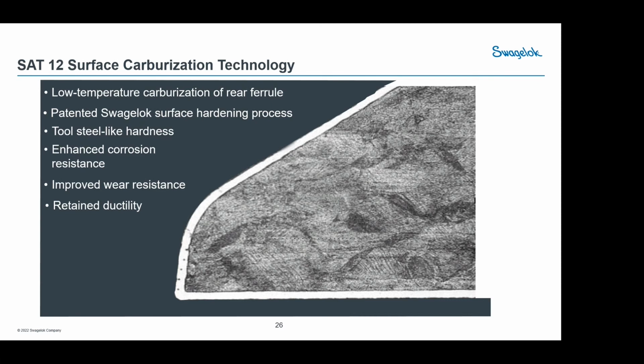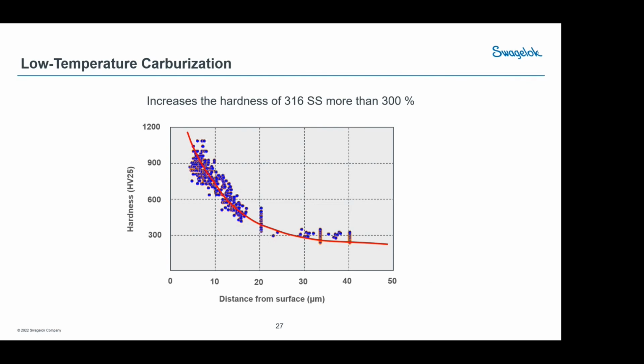Most importantly, though, as this moves through plastic deformation, it does not crack. So remember, cracks cause hydrogen to be able to enter into the products and cause issues. There are other ways to harden stainless that are chemical, but they crack as soon as they start to move. So that's not a great way to make that work. So it really adds to wear resistance and gives us a very hard surface. Up near the surface, where we've added all the carbon, we're up into a Vickers 25 scale of 900 to 1200 Vickers, which is really what tool steel is. And we've added hardness down into the area of 20 to 30, 40 micrometers into the part.